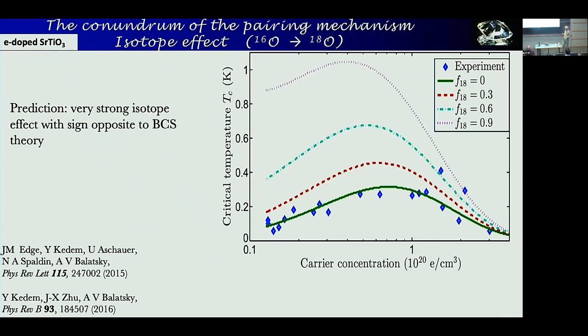Now, there have been other proposals for pairing, and that came from Edge, Kedem, Aschauer, Spaldin, and Balatsky. They said, okay, let's assume that you do couple to these soft ferroelectric modes. If you make that assumption, you find that you can reproduce this dome over here as a function of doping, and if you now make your system gradually more ferroelectric, you would see this Tc go up. So by moving it closer to the quantum critical point where it becomes ferroelectric, Tc would go up, and also the dome would shift a little bit to the left.